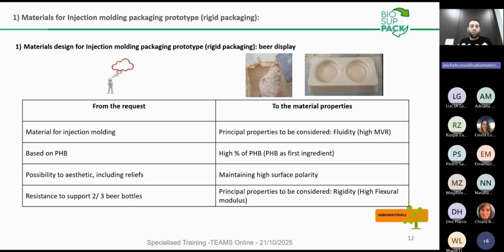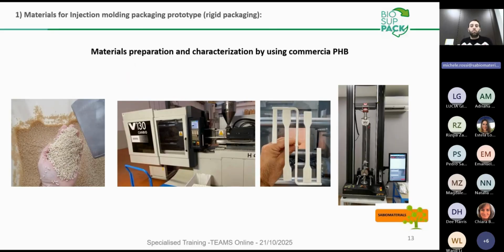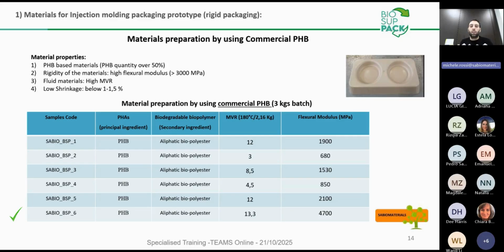So taking into consideration several parameters that we have identified from the requirements, we made some tests of material formulation, passing from the material preparation to the injection molding for the realization of the dog bone specimens, and at the end, for the first analysis, that permitted us to determine a series of compounds that we obtained based on polyhydroxyalkanoate, PHB in this case, that could present essentially a couple of requirements, meaning fluidity and flexural modulus.